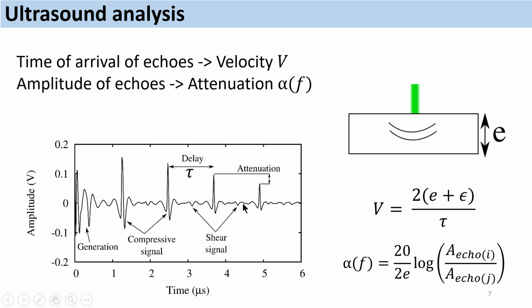Another parameter that can be interesting to evaluate is the attenuation. The attenuation corresponds to the decay between one echo and the subsequent echo. It can be evaluated in different manners, and often we look at this attenuation as alpha, which is a function of the frequency. So we know that this attenuation will be different at every frequency of these ultrasonic pulses. We divide by the propagation distance so as to have an attenuation per unit length, so as to be independent of the thickness of the sample.